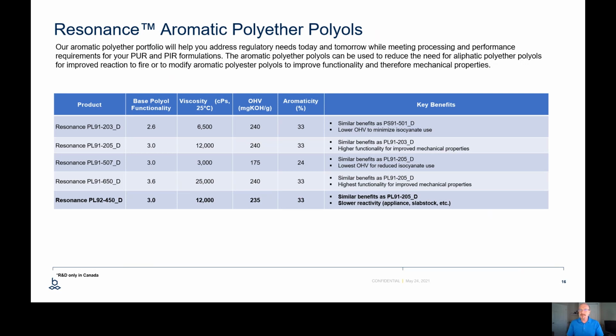So we were quite encouraged when we saw these materials and are suggesting these resonance high aromatic materials for your consideration as additives, not as a replacement for your polyols, but as an additive in 5 parts or 10 parts or 15 parts in your particular system to be able to either reduce the fire retardant, to be able to improve the odor of a particular system, or maybe you want to swap to a new fire retardant, for example, going from halogenated to non-halogenated, but you're concerned with the reaction to fire. Use a small amount of our material and you should be able to see an improvement in reaction to fire.